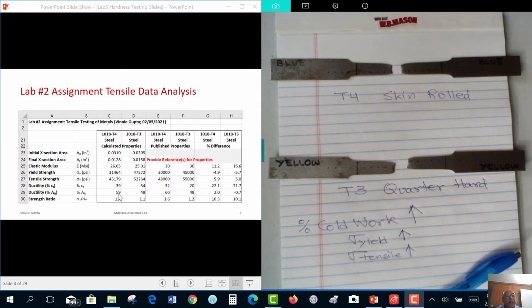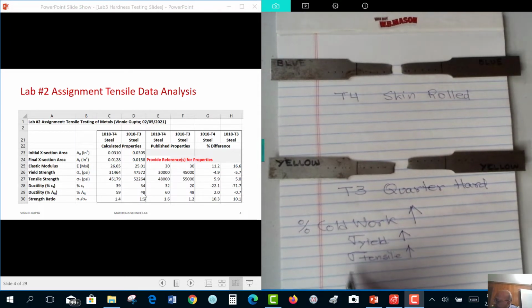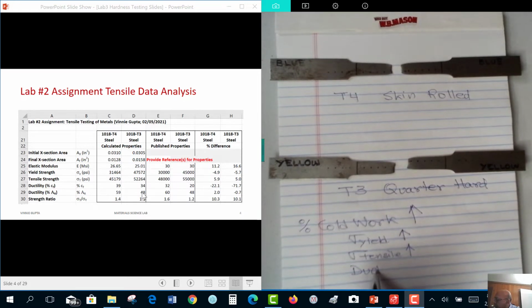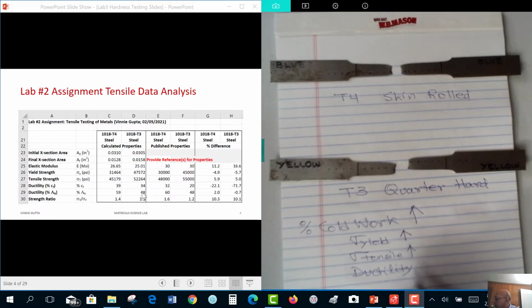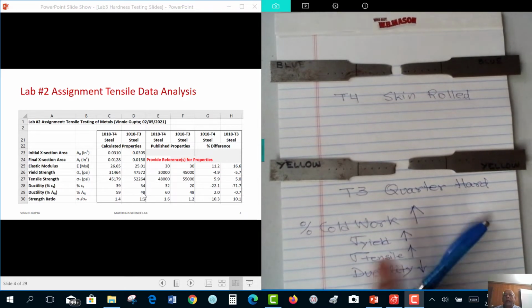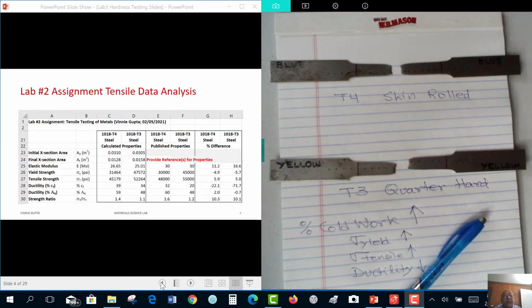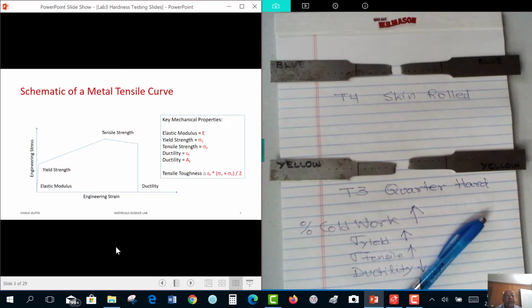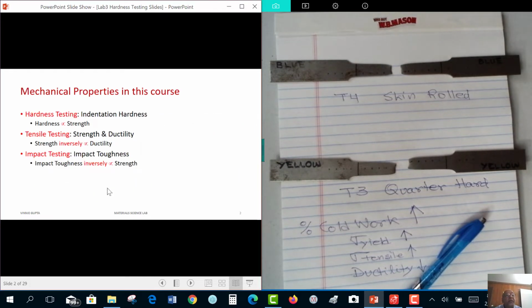But on the other hand, we decrease ductility, both measures of ductility, elongation to failure, as well as percentage area reduction. So we decrease ductility. And this is what I mentioned in my big picture. This is what we see, that strength is inverse with ductility.